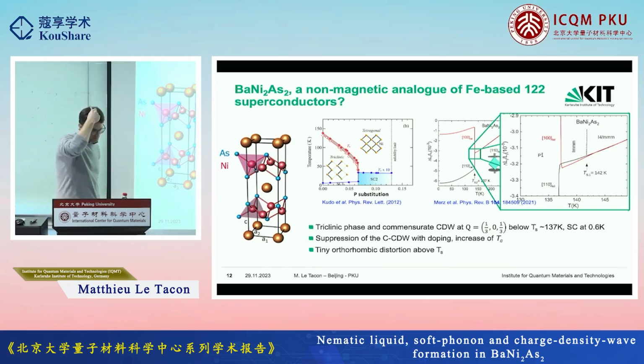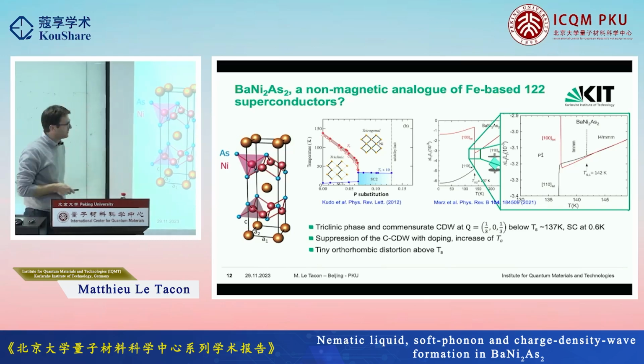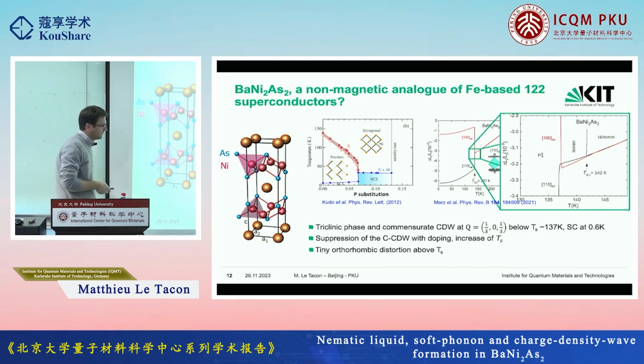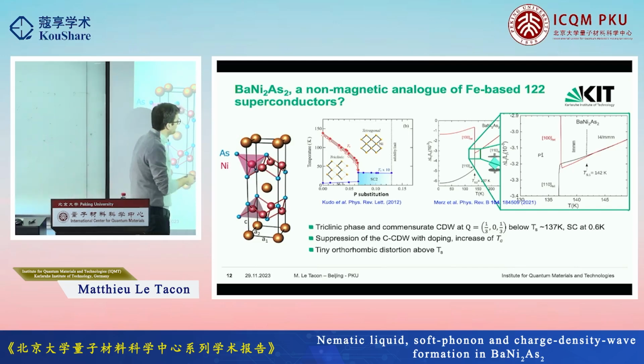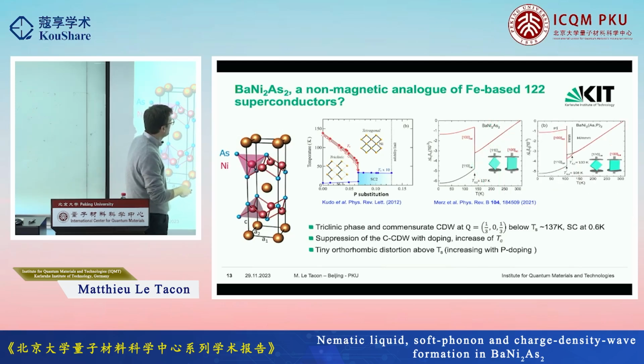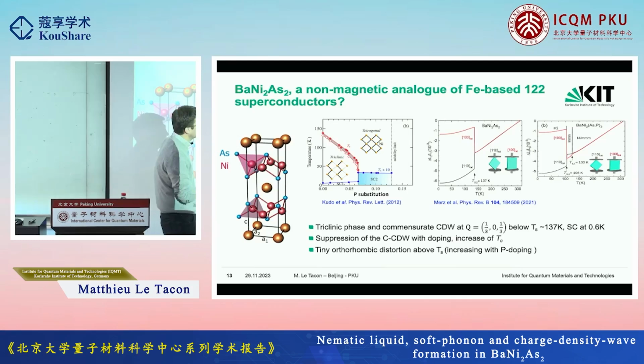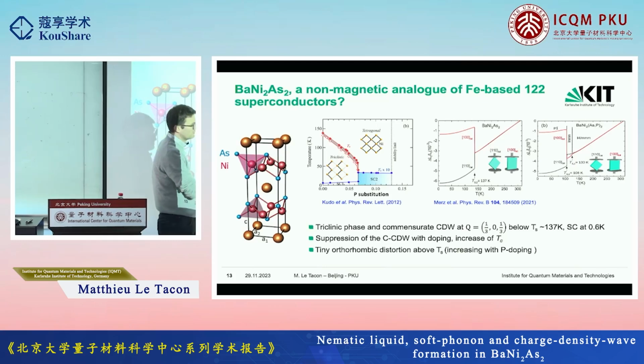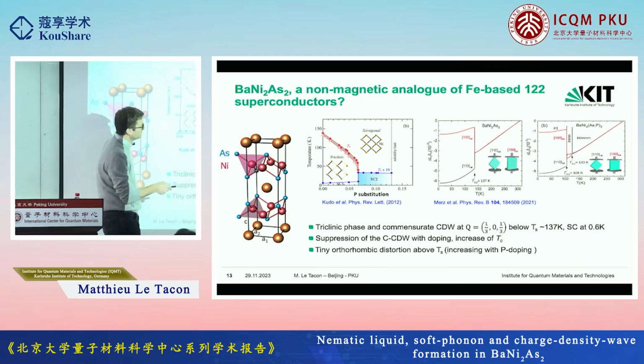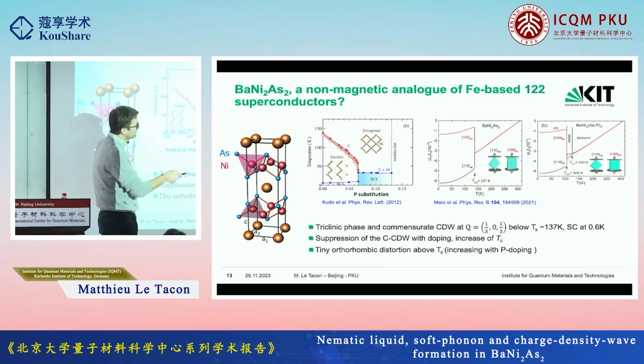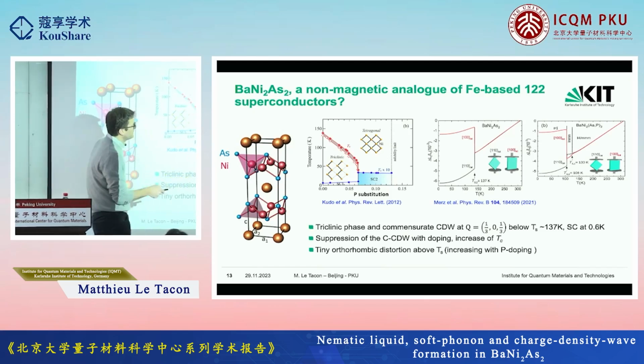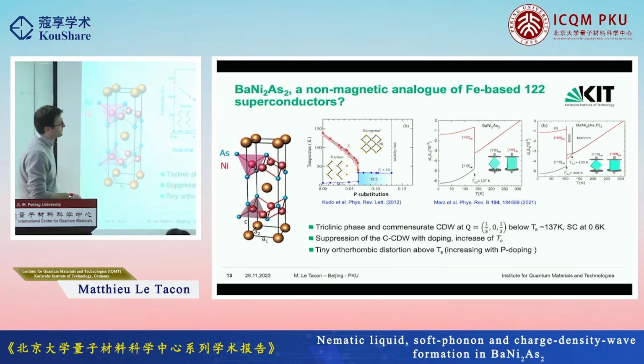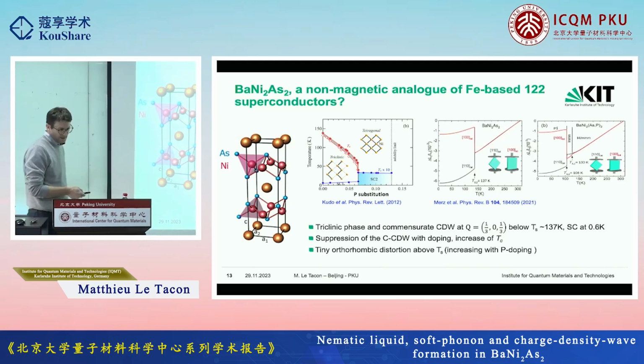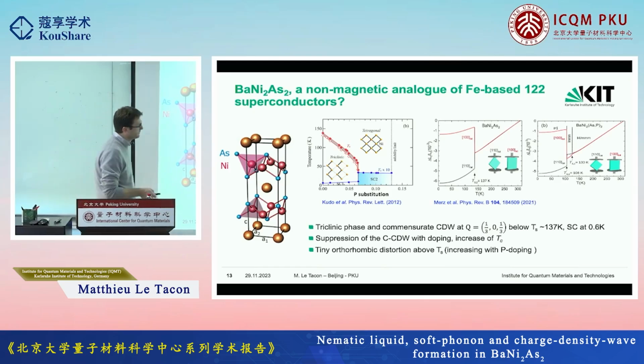When we first observed that, the reviewers were quite tough, and they asked for more tests. So we looked at the phosphorus-doped compound, and in the phosphorus compound, I think this is more obvious. You nicely see now a second order phase transition above the tricritical transition. You suppress the transition temperature a bit, and you now nicely see this. So we thought, okay, now there's clearly evidence for this orthorhombic distortion, and we can look into that in more detail and try to learn something.